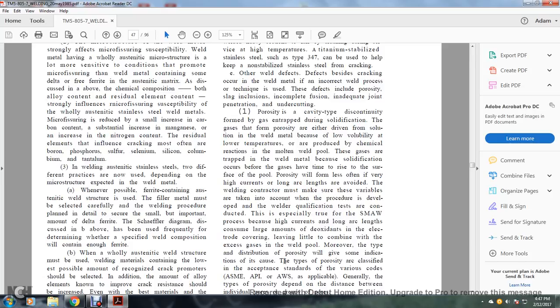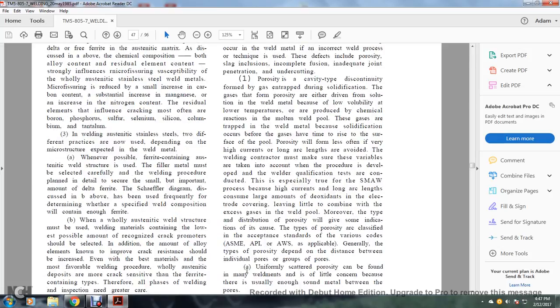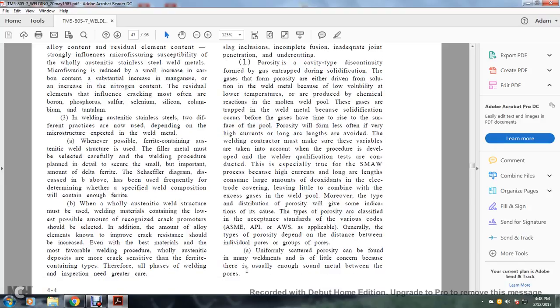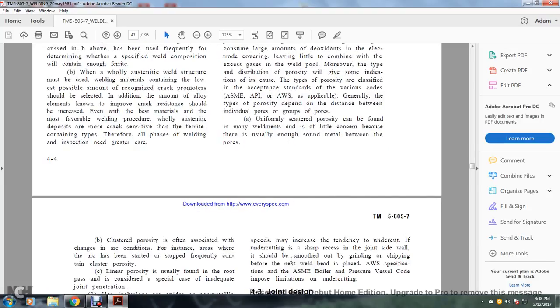The type of porosity is classified in the acceptance standards of the various codes, where the American Society of Mechanical Engineers, American Petroleum Institute, or American Welding Society is applicable. In general, the type of porosity depends on the distance between the individual pores or groups of pores. Uniformly scattered porosity can be found in many weldments, with little concern because there is usually enough sound metal between the pores.